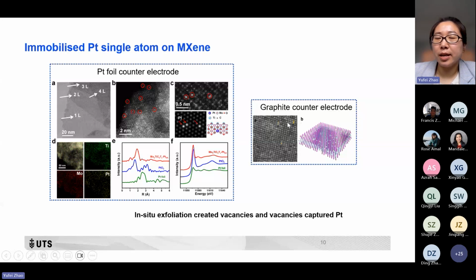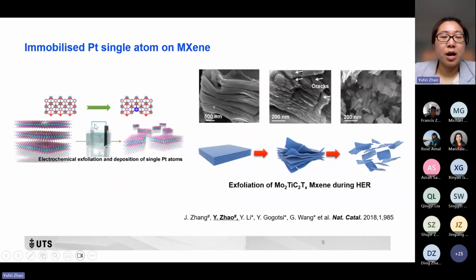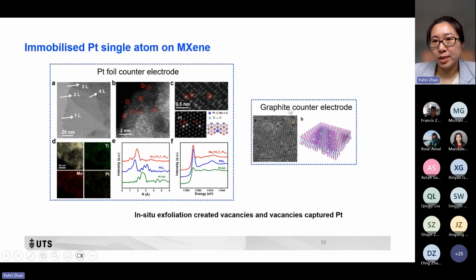by exchanging the counter electrode here from the platinum foil to the graphite rod. When we utilize the graphite rod as a counter electrode, that means there's no platinum in this system. We found a lot of vacancies have been formed on the surface of this MXene. So by comparing these two images, we assume that the platinum has occupied these vacancies to form the single atom